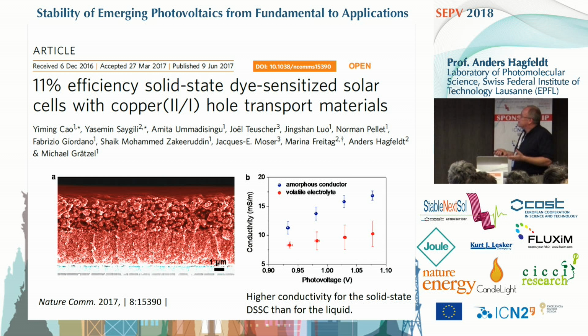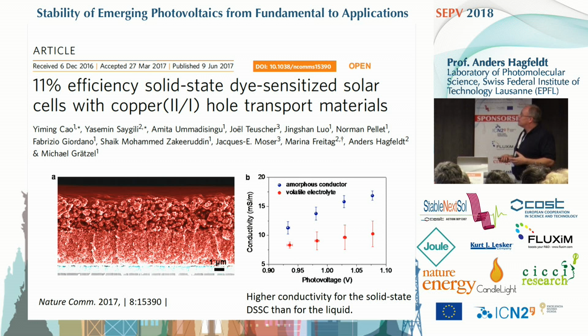Our best efficiency here is 11% at the moment, so very close to the liquid data, let's say. And it's the best solid state dye sensitized cell efficiency as far as we know. So that's a little bit of the update of the dye sensitized cell. Marina will talk more about it tomorrow.